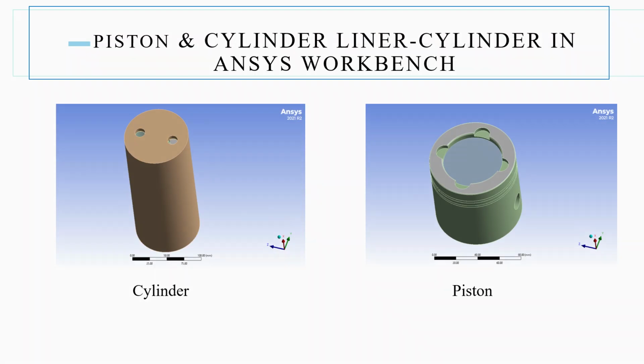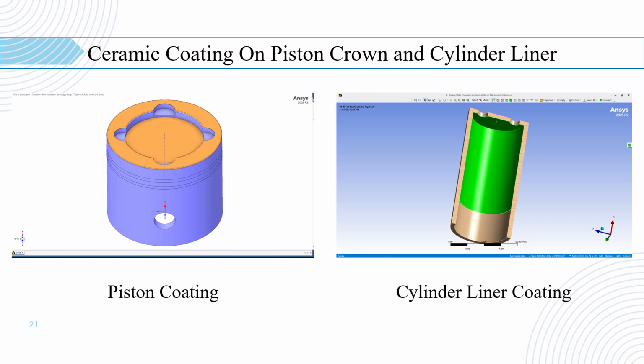Next, here we show the uncoated and the coated simulation model. This is the uncoated model, which has direct metal to gas contact leading to high heat conduction. This one is the coated model, which includes the YSZ layer on the piston crown and beside it the cylinder liner, and this layer acts as an insulation barrier reducing the heat flow into the metal.